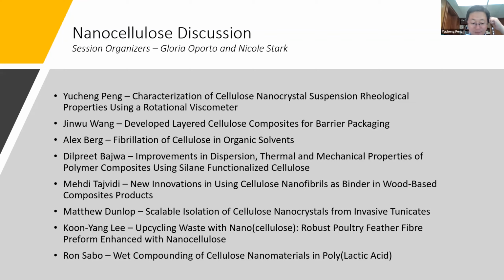Oh, that's a very good question. Actually, we did an extra experiment. The presentation here mainly focuses on cellulose nanocrystals, and we tried the same method on cellulose nanofibrils. But I just want to mention that those are two different cellulose fibers produced by different processes. When we tried to use the rotational viscometer on the nanofiber cellulose, actually it doesn't work. Since the fibers are longer, probably with a higher aspect ratio, it takes a long time to get consistent or stable readings from the rotational viscometer. We spent a lot of time doing that, but obviously this is probably not a suitable method for the nanofiber cellulose.